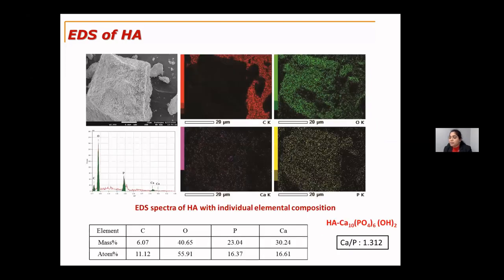Along with this, we performed the EDS spectrum for the hydroxyapatite. We chose to check the chemical composition of the hydroxyapatite. As we see, the chemical formula for the hydroxyapatite is Ca10(PO4)6(OH)2. So we do the elemental composition and the chemical composition for the hydroxyapatite particle. This is the elemental composition. I have chosen to show only carbon, oxygen, calcium, and phosphorus, which are the major elements. We can see definitely that the synthesized nano hydroxyapatite particles have all the chemical composition that was defined in the chemical formula for the hydroxyapatite.